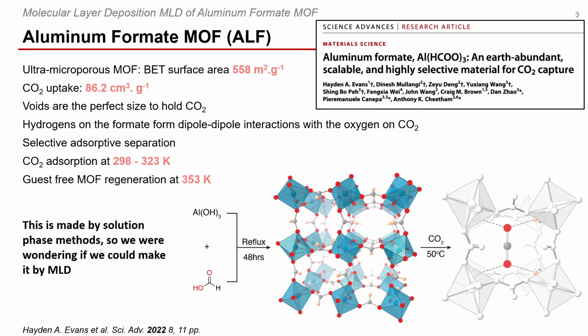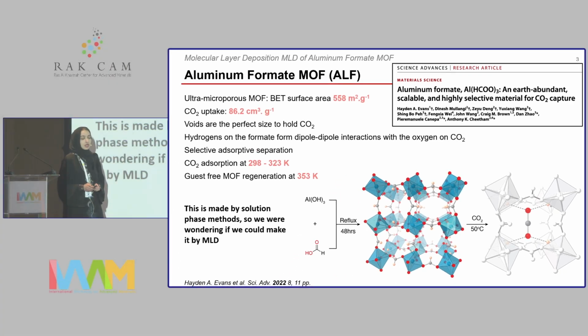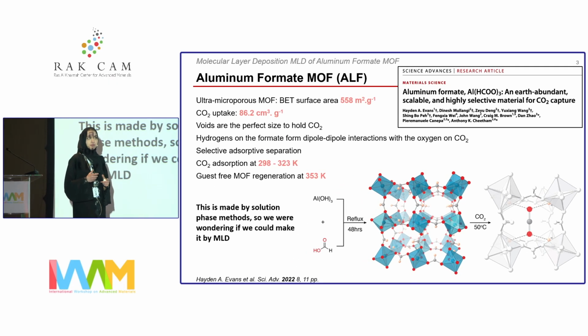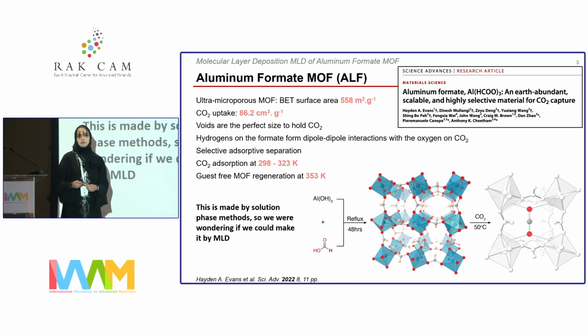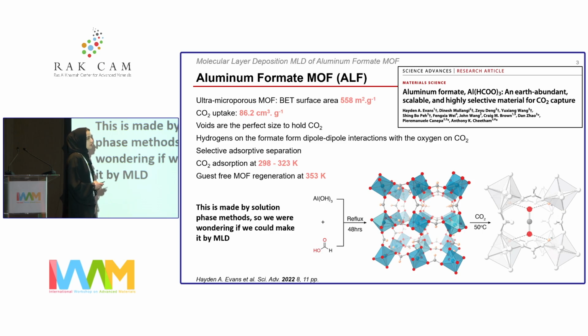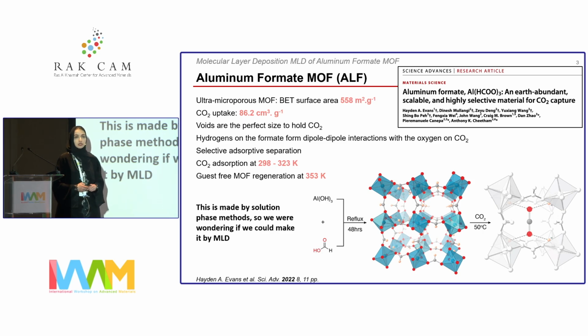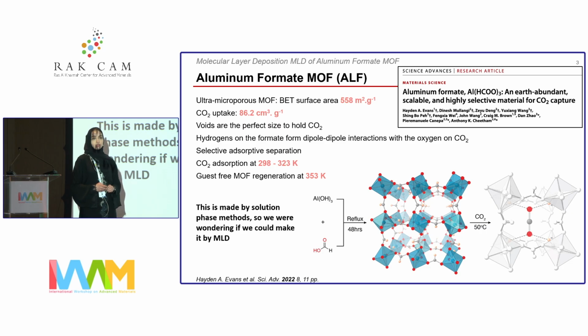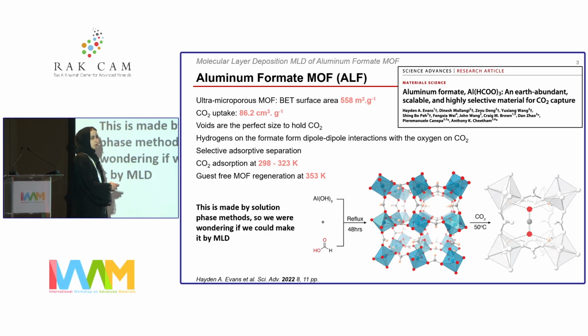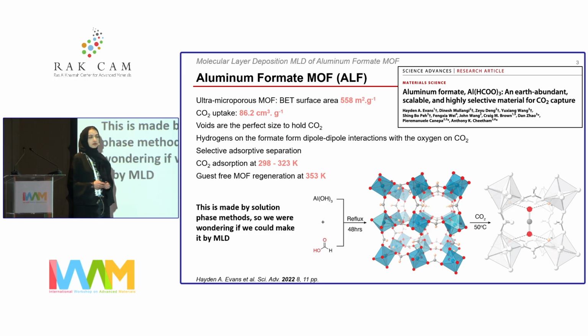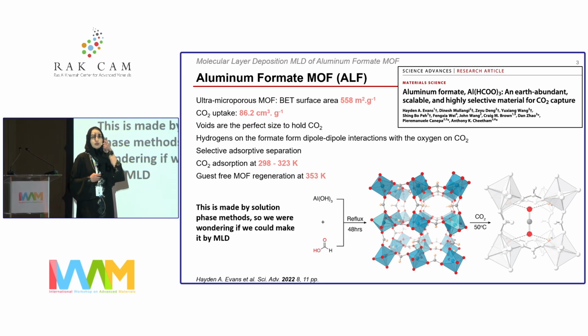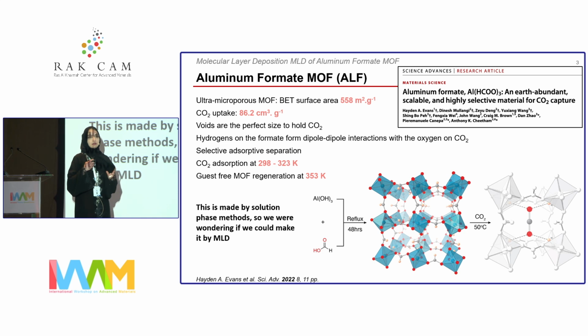I came from an ALD lab. I know this is jargon. I'm going to let you know what that is in a second. Atomic layer deposition. We love volatile compounds because we can translate materials into microelectronics devices by making a thin film out of it. That's why. So we wanted to see if we can translate this MOF structure into an ultra-thin film and integrate it into microelectronic devices. And the way we know that we got this MOF on the surface, the right structure we're looking for, is if it was crystalline on the surface, and if it was going to retain the selective adsorption of carbon dioxide. So that's what we wanted to test here.